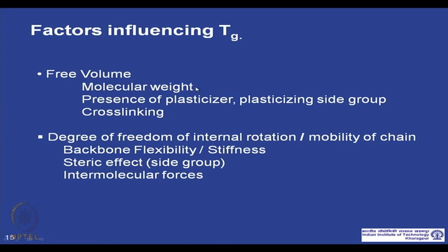Those are free volumes, and with increasing temperature the free volume typically increases, and the material becomes less and less dense. Free volume of a polymer material depends on molecular weight, presence of plasticizers or plasticizing side groups, and cross linking. We will discuss the effect of these in a little more detail with examples.